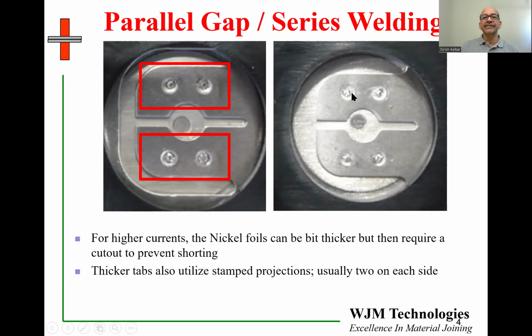So as the nickel tabs become thicker, it becomes necessary to use projections. It can be 1 projection on each side, and can also be 2 projections on each side. You also notice in this design that there is a cutout in the nickel tab. This is made to prevent the current from shorting across the nickel tab. If this cutout was not there, the current may want to short directly across and not be forced to go down into the can and then come back up. So the cutout has to be long enough that the alternative of going across is too cumbersome, and the current will flow into the can, go through it, and come back up through these tabs.